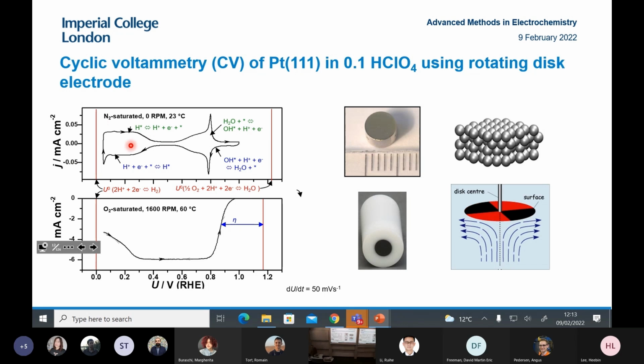Here we're cycling the potential up and down, in nitrogen. The positive current means you have an oxidation taking place, and the negative current means you have a reduction taking place. Platinum 111 is the only surface, as far as I know, at least among platinum-based surfaces, where you have a very well-defined region where OH is adsorbing, and a region where hydrogen is adsorbing. On all other surfaces, you usually get a mixture of hydrogen and OH adsorbing in the same region. This is contrary to popular belief.